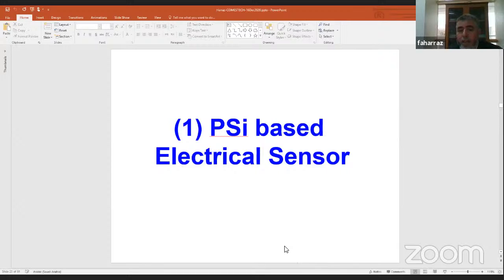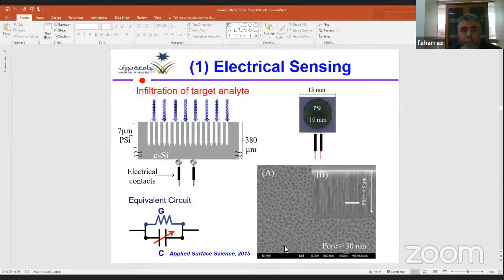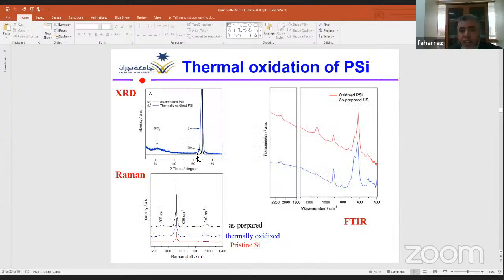Now, let me give you an example of utilization of a porous silicon-based electrical sensor. This is our porous layer. The thickness is around 7 micrometers, and the pore size is around 30 nanometers. It lies in the mesoporosity regime. Upon infiltration of this porous structure with some target analyte, the electrical properties will change. Here, we made some thermal oxidation of porous silicon just to stabilize the device.